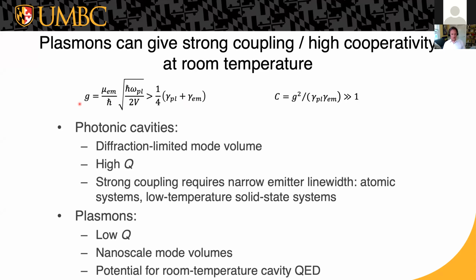But in plasmonic cavities, you're no longer limited by this diffraction limit. Their plasmon line width is very broad, the lifetime is very short, to the point where even room temperature thermal dephasing is smaller than the plasmon lifetime. So you have to get an even stronger coupling strength in order to reach the strong coupling regime. But you're no longer limited by the diffraction limit. You can get down to single nanometer dimensions for your mode volume and have the potential to really do this using single emitters at room temperature.